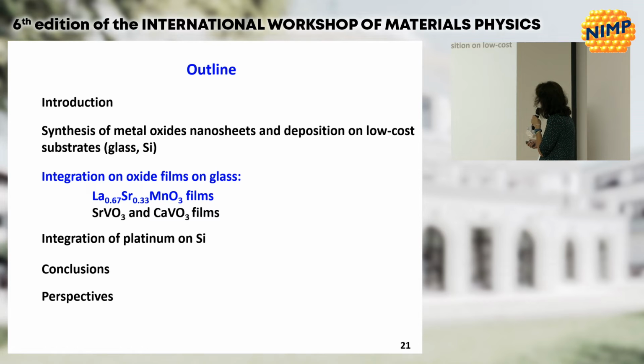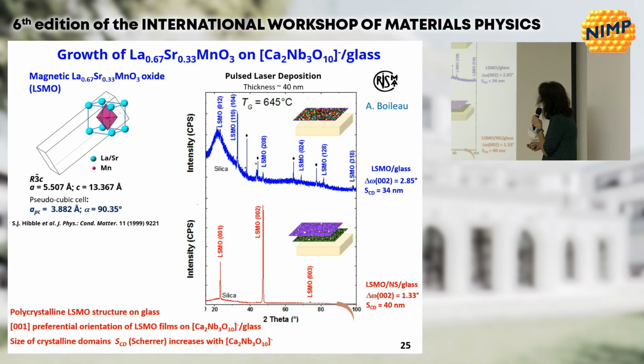So first with this manganite. The work was done by Alexis Boileau in CRISMAT. He deposited by pulsed laser deposition this magnetic oxide on glass directly, and he obtained something which is crystalline at least, but polycrystalline, as you can see. And when we deposited the same material on the nanosheet-covered glass, we have only one orientation, which is the one we expected. Also, you can see that the width of the rocking curve is smaller on nanosheets than on glass, and that the scattering domains are also larger.